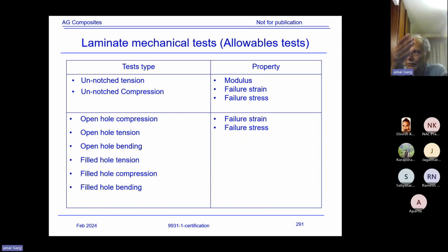Okay. Now, what happens, making the coupons like quarter-inch hole and testing for various batches. That is another thing. You have to determine the values for different batches, like 5 batches or 6 batches of materials. So that means almost like 25, 30 coupons you'll be producing. You have done the statistical analysis for that parameter, which is just a quasi-isotropic and thickness of like 2 millimeter thick coupon. Okay. Now, what happens? This you have done at room temperature. But you want to determine the property at hot wet condition also.